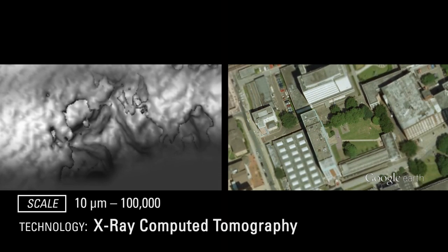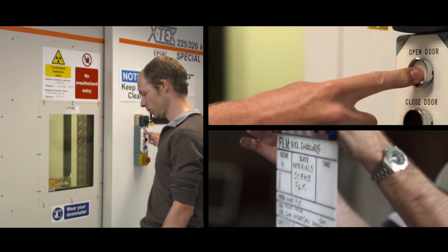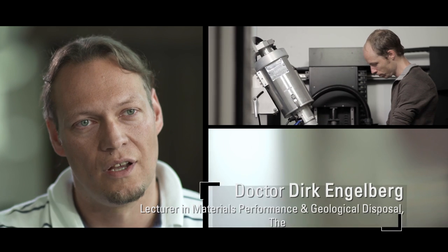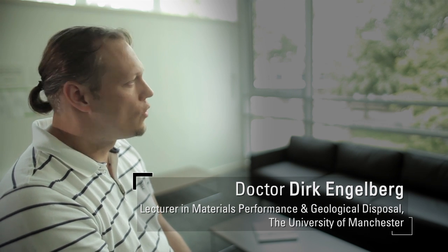Now that we've scanned the surface at the submillimetre level, we need to look more closely at the pit that can lead to cracking at the micron level. In the next step of our journey, we go 100 times closer to the 10 micron scale — equivalent to moving to the square in which the ICAM building is located. By using X-ray computer tomography, we can look non-destructively at the nucleation of local corrosion sites, identify pitting corrosion, and distinguish different corrosion mechanisms.